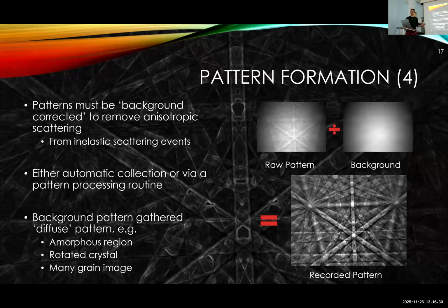In practice, we get a few more little details that happen. So we get the raw diffraction pattern looks like this. This contains effectively a diffuse background where the electrons have scattered and lost way more energy. So the electrons in the Kikuchi pattern have lost at most a couple of eV off the primary beam. These ones are typically higher energy loss electrons.